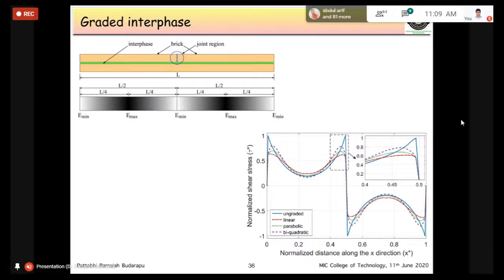So the peak stresses must be reduced. You can see the peak stresses are reduced by almost 40%, from 1 to 0.6, by linearly grading. That is quite significant.